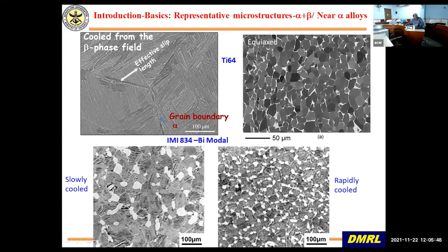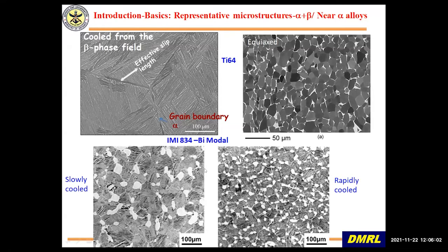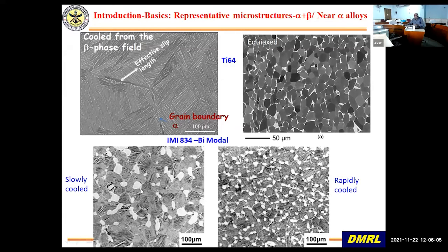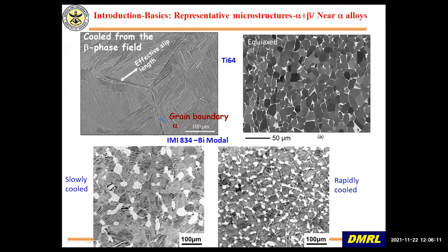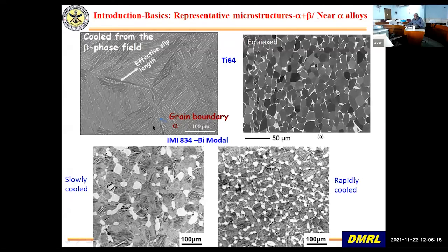Then there is also something known as bimodal structure. This is an example of IMI 834. It's a high temperature titanium alloy, which is used in aero engines, in the compressors, etc. So here you can see why it is called bimodal is because you have got this primary alpha and transformed beta, and the grain sizes, as you can see, have reduced quite a lot from this to this. This kind of microstructure is very desirable if you want good fatigue and all. If you cool faster, you get a slightly finer microstructure. You get finer beta and also finer grain size, and also lath size is finer. So this is also a bimodal microstructure.